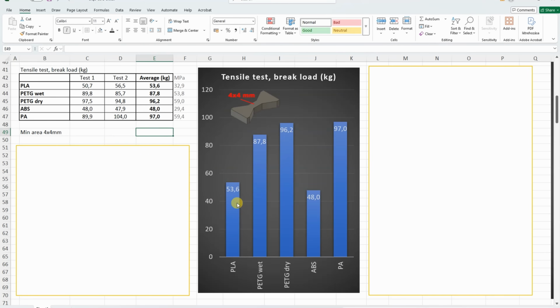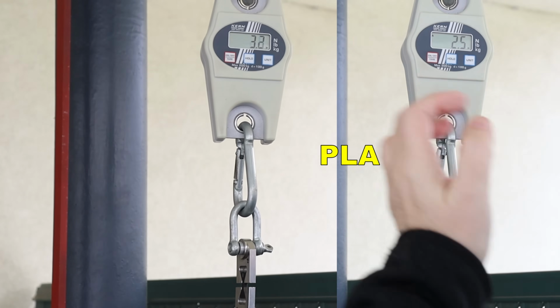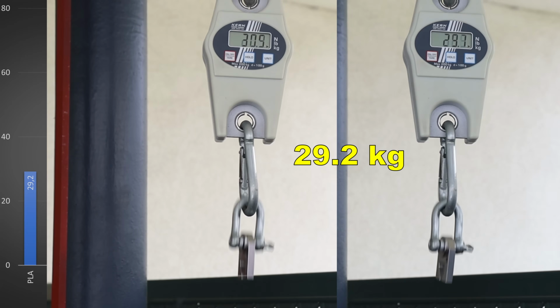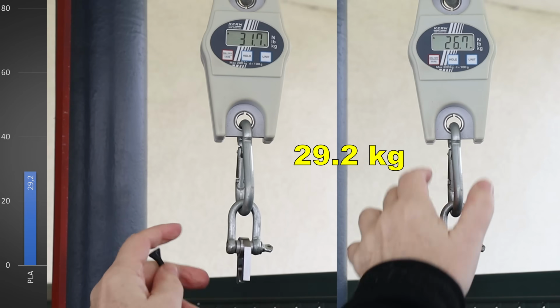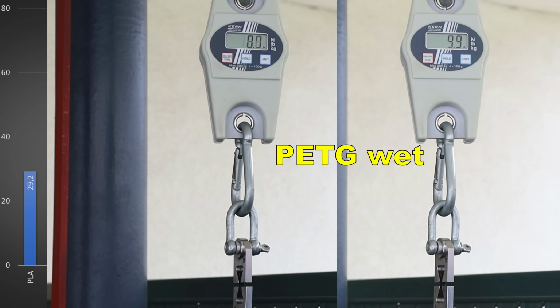Surprisingly low numbers for the PLA and the ABS. PETG very good, but look at this, drying helps. The difference is not big but noticeable, and similar value for the PA. Layer adhesion with vertically printed objects. Now wet.